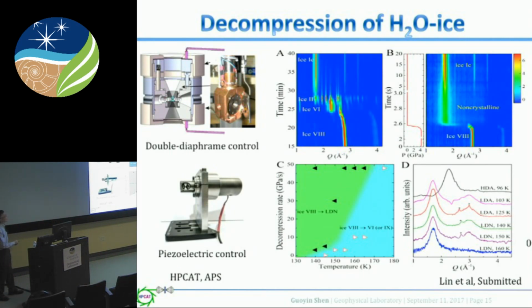This is actually already at ambient pressure, or even in vacuum because of the cryostat. And then what we see is that the non-crystalline ice clearly appeared. The appearance actually lasts for several seconds, enough time for us to collect the liquid structure data. And then eventually, after a few seconds, ice 1 grows from that, let's call it non-crystalline ice at this point.